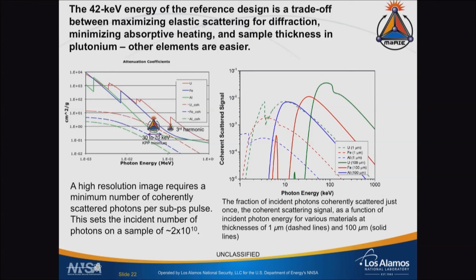And we believe that you can basically get to a situation out in the high tens of keVs where for thicker 100 micron type samples, as many as about 1% of the photons will give you good signal. You still have to live with that other 99% of the X-rays that come in and heat your sample up, but you're spreading them out over a bigger region to do mesoscale sampling.